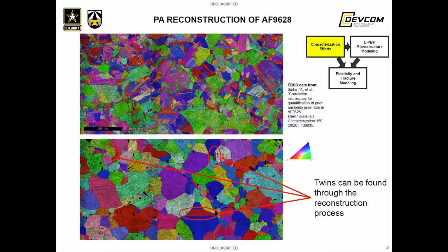Once a suitable set of 3 martensite grains are found to have a common possible parent, such as in the schematic shown in the previous slide, their neighbors are then checked iteratively to find neighbors to that cluster that have possible parents that are also within tolerance. The parent austenite grain is then defined once the cluster can no longer continue growing. Often there are regions where those clusters overlap each other and you have to further subdivide those two clusters. This is often caused by the presence of twinning within the parent austenite structure. A few twins are shown in this slide here that have been identified. The method to perform this cleanup has also been automated, and so this prior austenite reconstruction has been automated entirely.